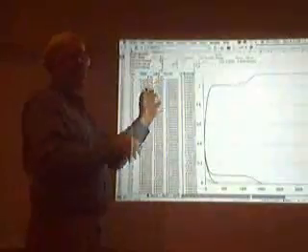Just a question. Which concentration must you use to have such a solution? Well, this is arbitrary because we just put numbers in here. But Ribo used some real physical data to try to get this parameter. Anyhow, we are just demonstrating how the equations behave. It's general, but the only assumption is that clusters can be selectively incorporated. If you believe that, then this will happen. There may be other things that happen. There may be nucleation, there may be grain boundaries, there may be anything. But this must happen if you can incorporate crystals selectively.